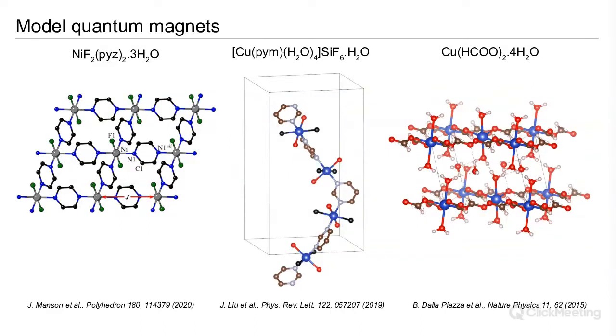And this gives us a model system in which, as Jamie Manson did in this paper, we can explore the way in which one can tune anisotropies at the nickel site, because it creates a model system in which we can have a handle on one particular aspect of the magnetic properties. Another case here, we can create these so-called chiral chains. So this is arguably one of the most one-dimensional magnetic materials that's known. In this case, we can worry about the effect of the chirality on the magnetic system and the fact that we build in staggered fields from g-tensor anisotropy. And in this particular case, it gives rise to very exotic magnetic excitations that can travel up and down the chains.